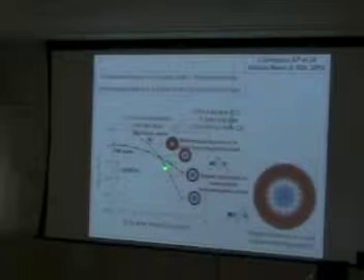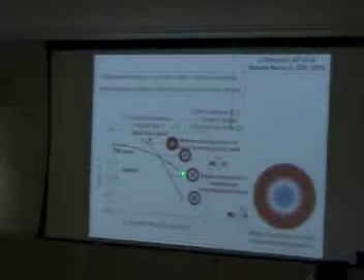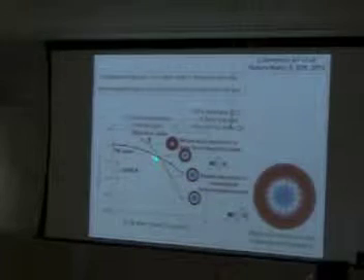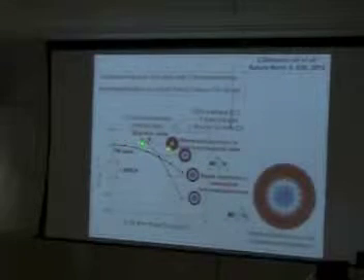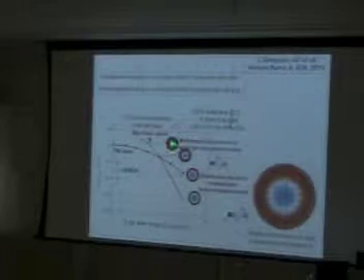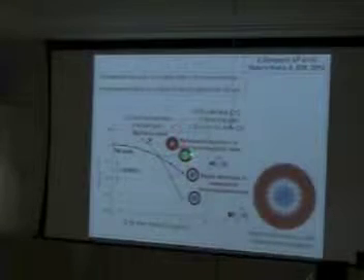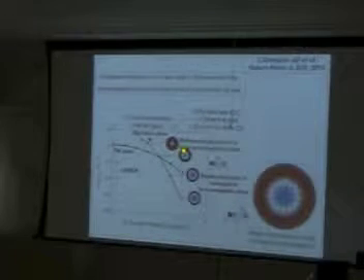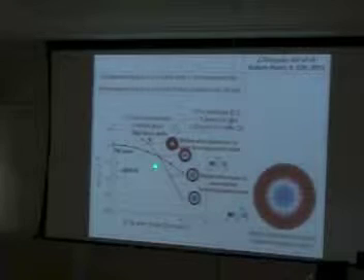You can see that in this range, the skyrmion state is more stable than the ferromagnetic. It's not so interesting for us. The interesting regime for many applications is this one, where we have metastable skyrmion states in a ferromagnetic disk, protected by the topological protection.